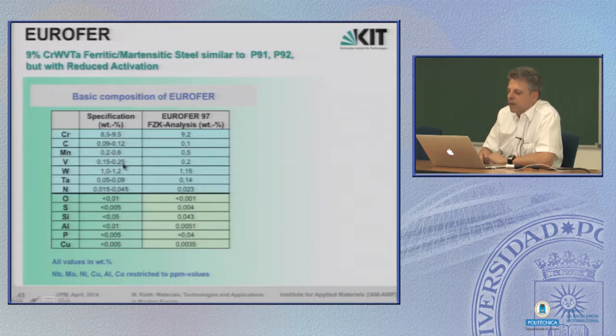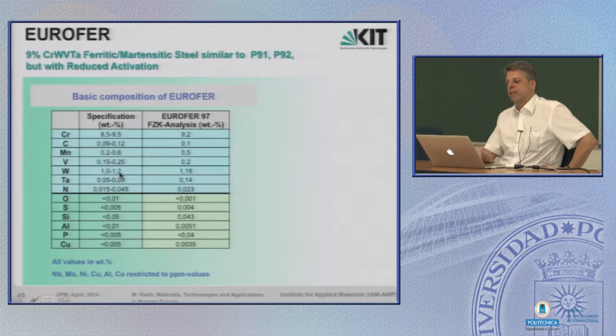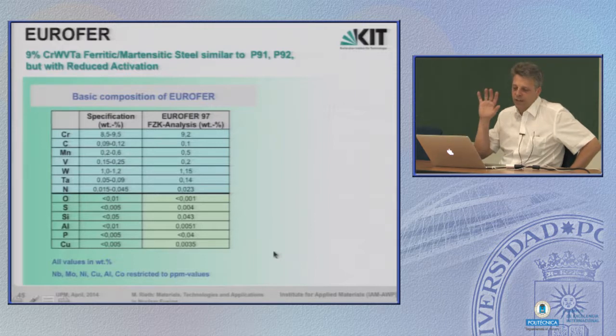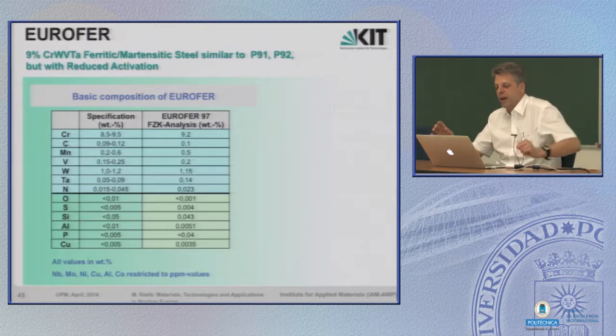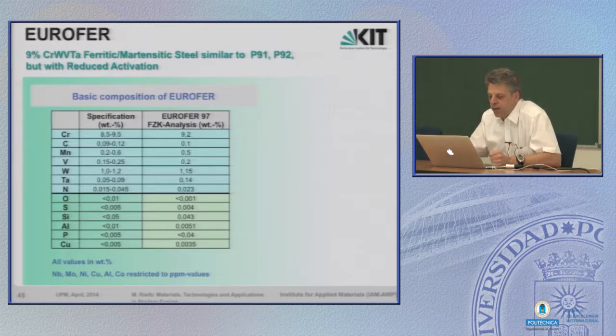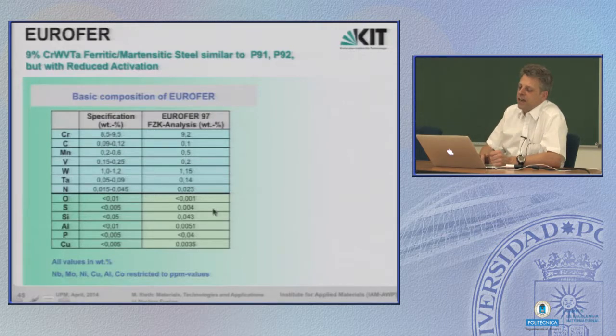Manganese, some addition of vanadium, 1% tungsten, some tantalum, some nitrogen, and that's it. Everything else is not wanted in the steel. So we want to, or you have to, produce it very purely to get rid of all these other elements, and this makes this material more expensive.